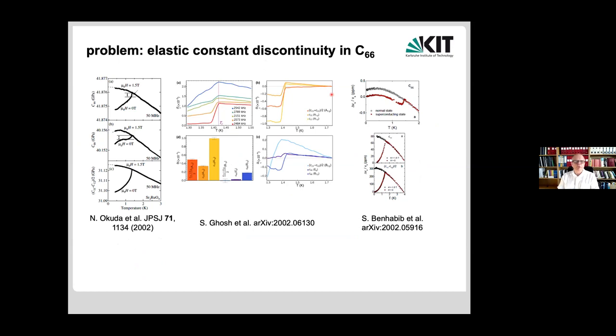Of course, with every theory, there's a problem. And the biggest problem we see with this approach is that we have one indication from true bulk measurements that says something about the nature of the pairing state, which is the elastic constant discontinuity, particularly the one C66, an elastic constant that transforms non-trivially, not like A1g. And here in this work by Brad Ramshaw and collaborators, we see that there is a discontinuity. You see it here in this elastic constant.